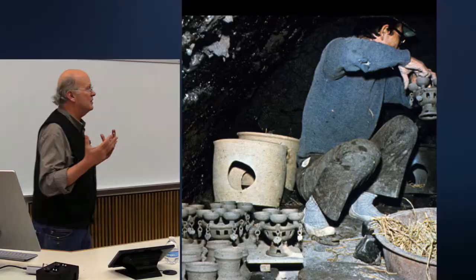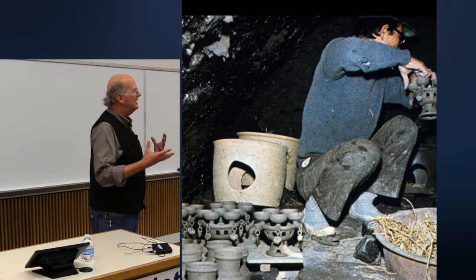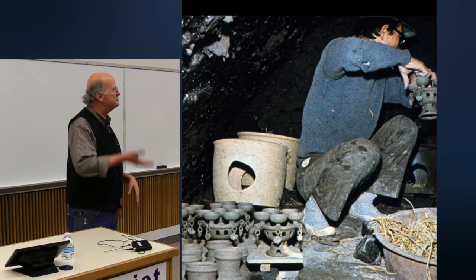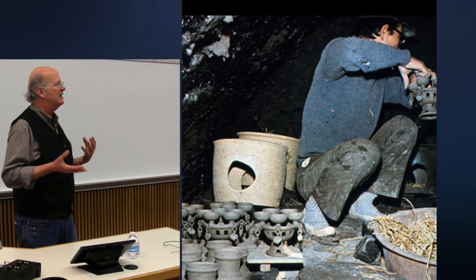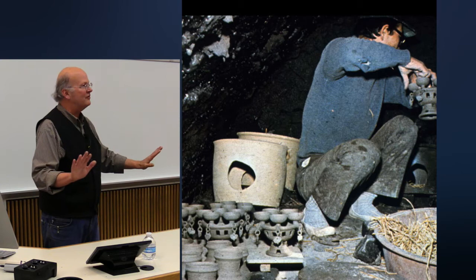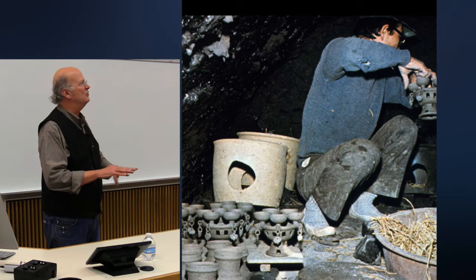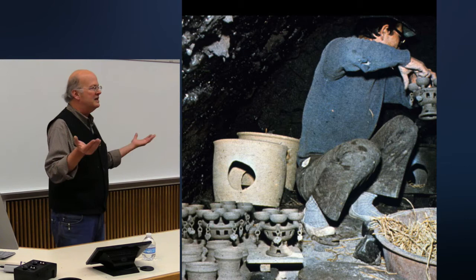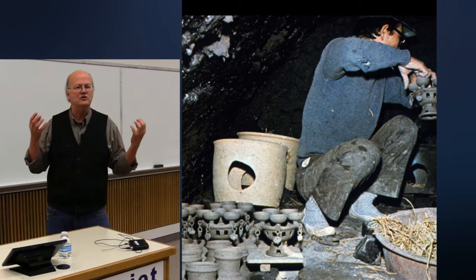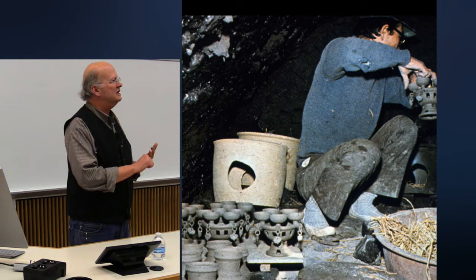Well, in my experience, any fuel, any wood that's left at the end of a firing burns immediately because air rushes in and consumes it, especially when the temperature is high. It does not stay in an unburned state unless you go to great lengths to quench it or douse it, cut off all the air. So what they were doing was to consciously seal fuel into the kiln and let it cool in that state. Then I thought, aha, using the atmosphere in the kiln to change the clay.